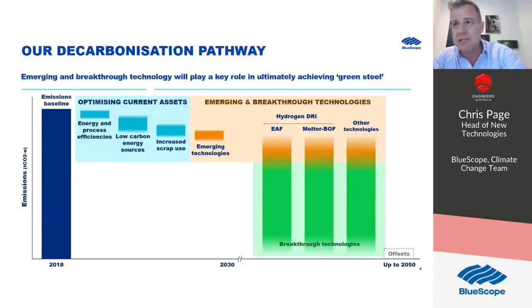Lower quality ores, the reason that the Pilbara type ores aren't considered as suitable for the DRI process is that they have a higher gangue content. That gangue content has to be removed. If you put it in an EAF, electric arc furnace, that will overwhelm that electric arc furnace and render it very inefficient, needing a lot more electricity to get the steel yield out of it. So for those reasons, we are looking together with Rio Tinto to see if we can solve the Pilbara ore problem through the DRI process.